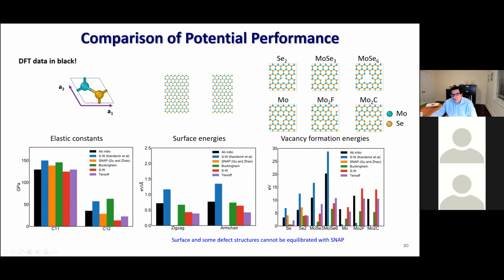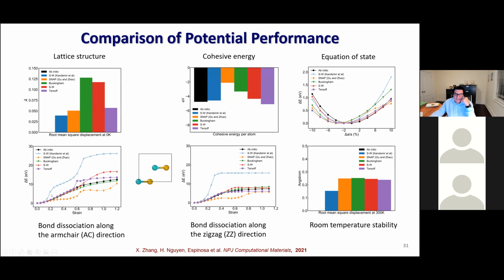Then you can start looking at more nonlinear behavior by looking at vacancies, and you can start removing two selenium atoms, a cluster of vacancy molybdenum, three selenium, and so on, many different types. And what you see is, again, those potentials I showed earlier have a lot of problems, but Tersoff, which is our parameterization, does not have perfect prediction, but more reasonable prediction. And the issue is that there is a trade-off, and that's what you are finding, what the potential can do. Dissociation, not surprisingly, we included in our screening, so the Tersoff and the other potential we parameterized follow the dissociation energies as a function of the stretching, but very poorly for the two potentials I showed you earlier.